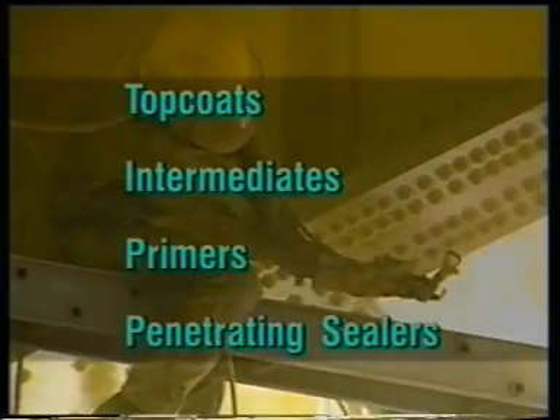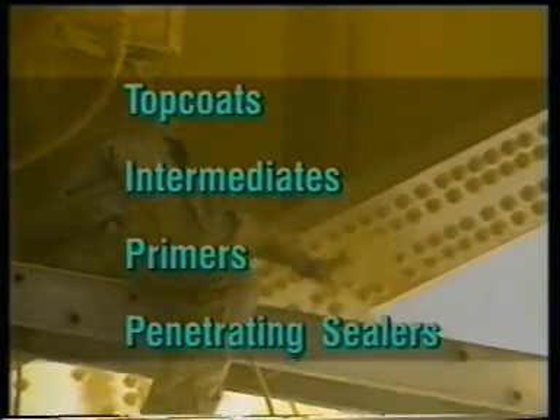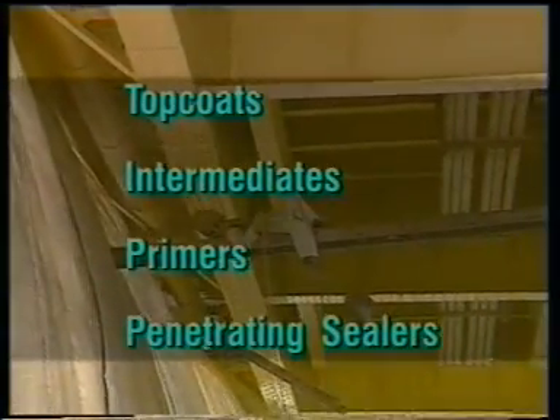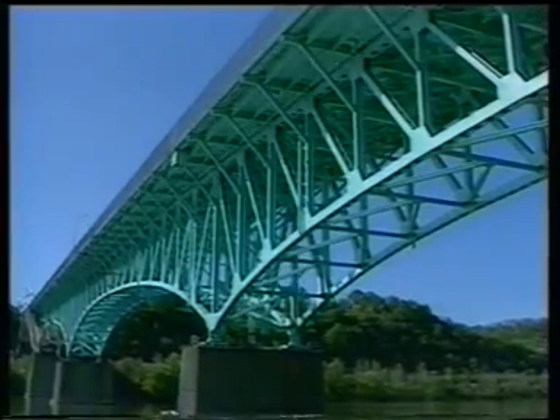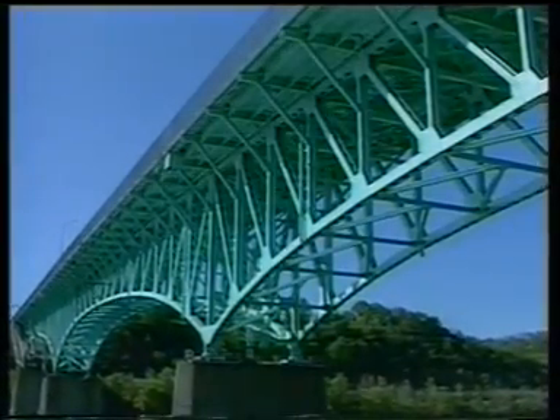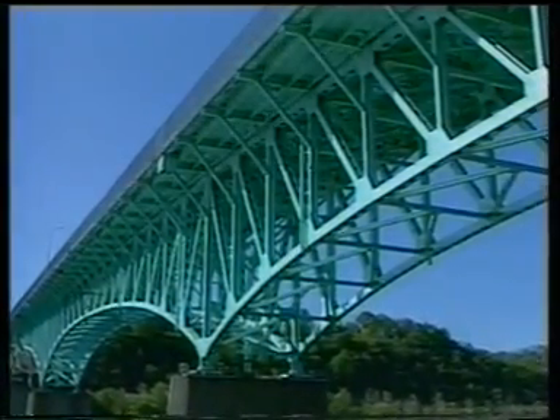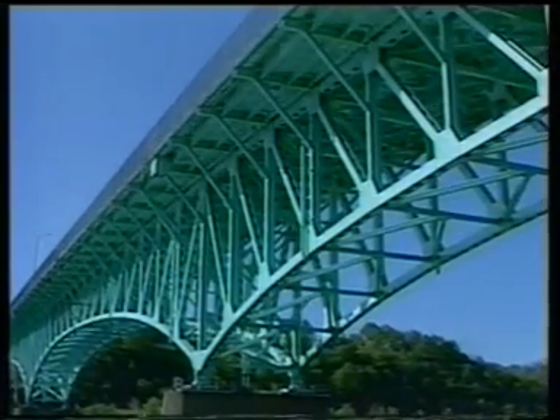Polyurethane coatings are manufactured as top coats, intermediates and primers, and penetrating sealers. Moisture-curing polyurethane primers harden to a smooth, dense finish that can be recoated quickly. In fact, on the Tarentum Bridge near Pittsburgh, the contractor applied the primer, intermediate coat, and even the top coat during a single 24-hour day.